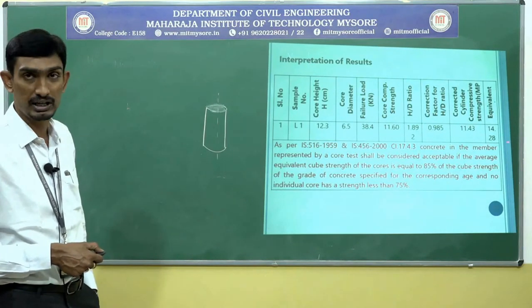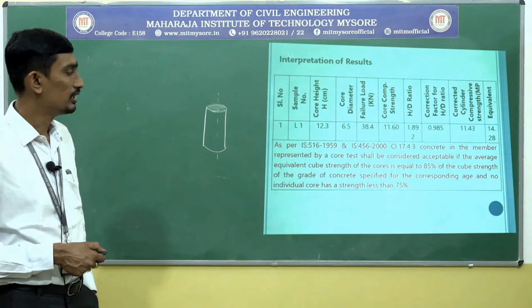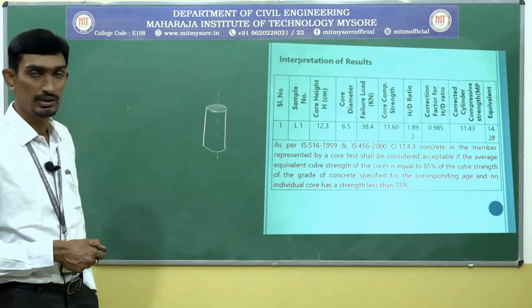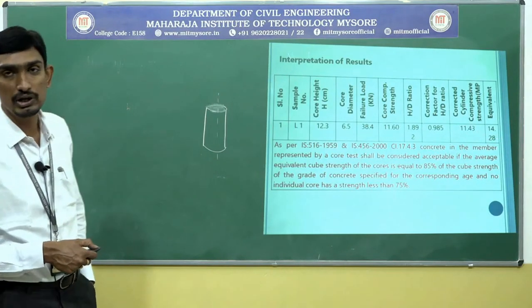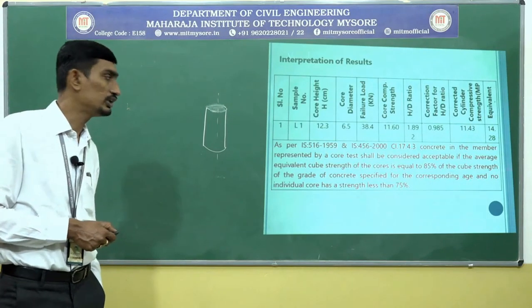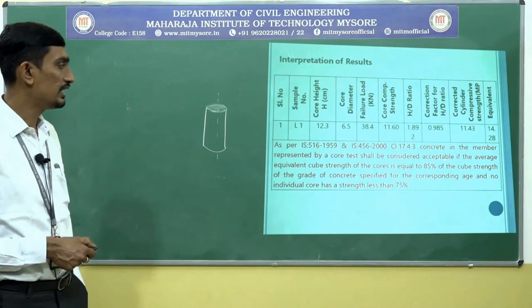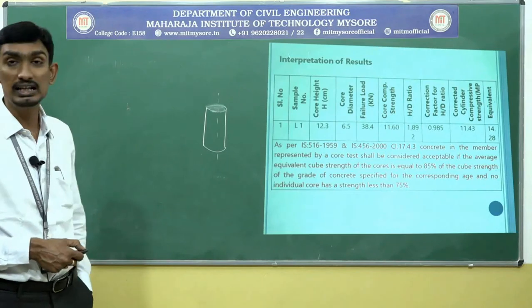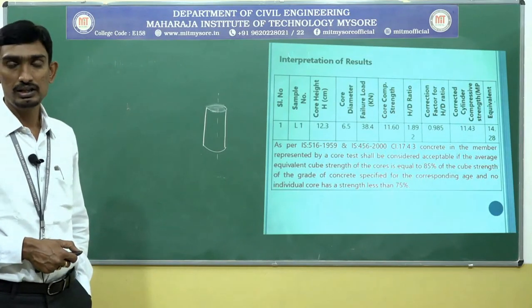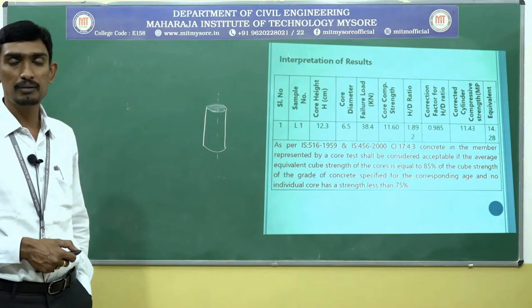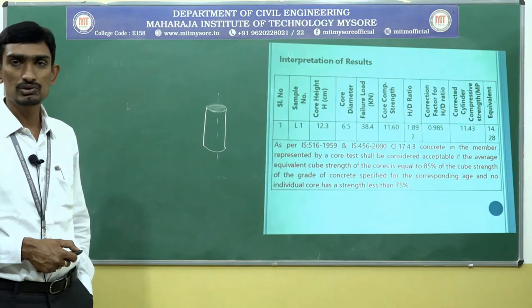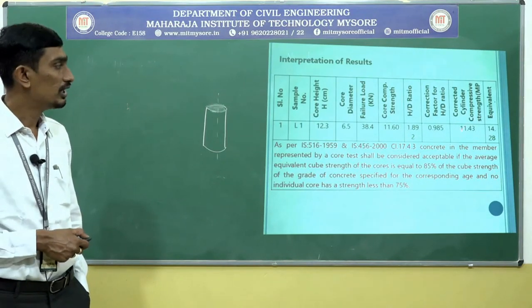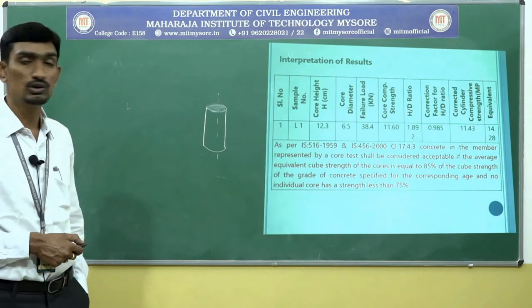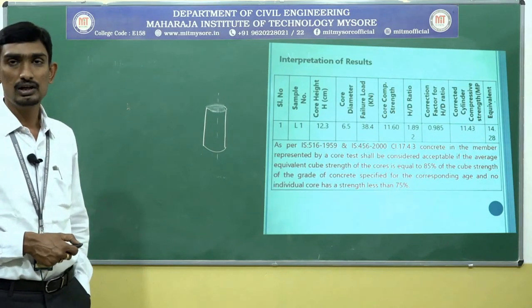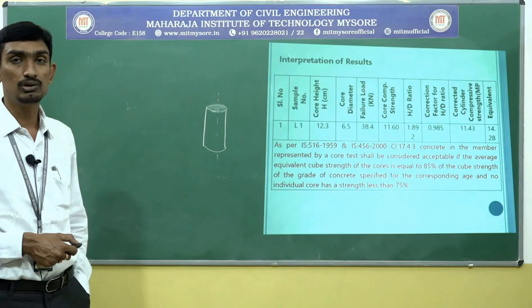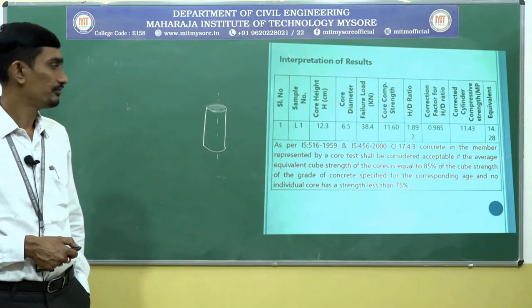For example, if it is M20, the average of whatever you calculate should possess at least 85% of the cube strength as a minimum value. That is 0.85 multiplied by 20. That is the compressive strength that the equivalent cube strength should possess. Otherwise, I cannot accept the concrete core specimen.